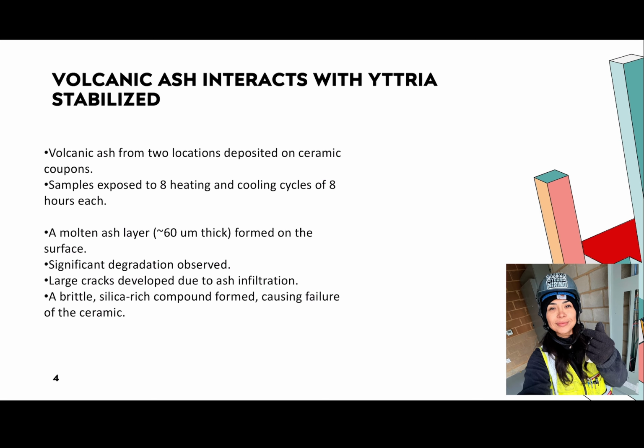As far as the volcanic ash interacting with yttria stabilized zirconia, the study looks at the interaction of 7YSZ ceramic used in jet engines with volcanic ash at 1350 degrees Celsius. That's what we're hyper focusing on right now. The volcanic ash from 2 locations is deposited on ceramic coupons, and the samples are exposed to 8 heating and cooling cycles of 8 hours each.